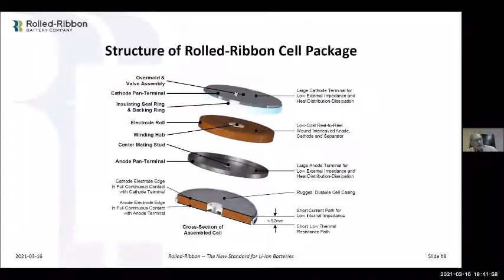And the way those cells are put together, if you look at it, we take a pan here, we have a seal here that insulates between the two pans. So we have two pans. Again, we cut a narrow ribbon of electrode, anode and cathode, and we interleave those together and we wind them up into this roll, and we expose the edges of that electrode here, and we wind that up into that large pellet you see, and then the edge of this comes in contact with the two pans, one on one side and one on the other. We put them together and we put it under pressure here.